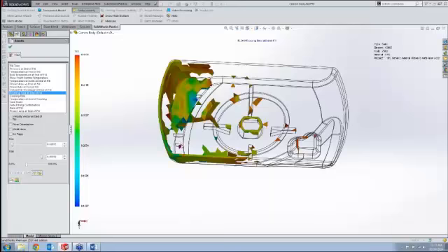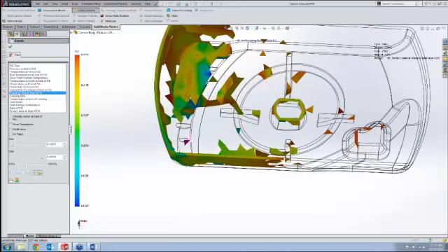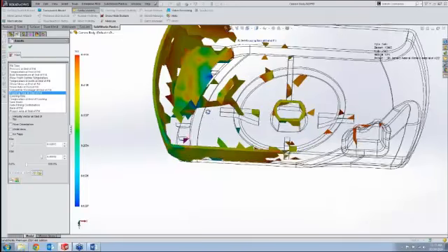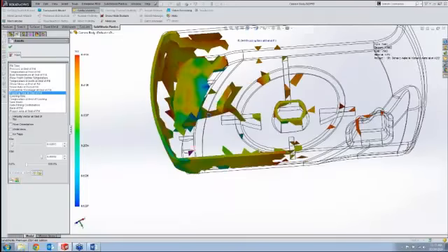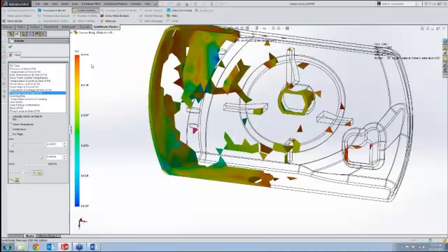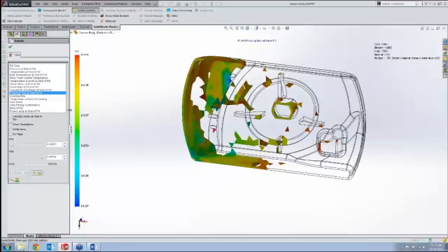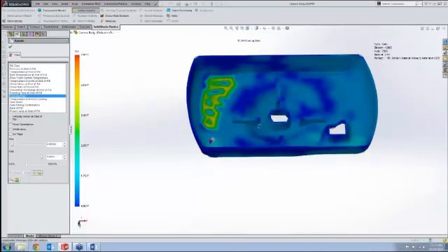And what that signifies is the plastic has turned to solid material at the plotted place here and given time frame within the flow. So if I have any of this solidified specifically at the gate location, the packing phase is no longer exerting pressure on the plastic and not doing its job. So what we're looking to make sure is that we don't have any gate freeze at this point on a part like this.